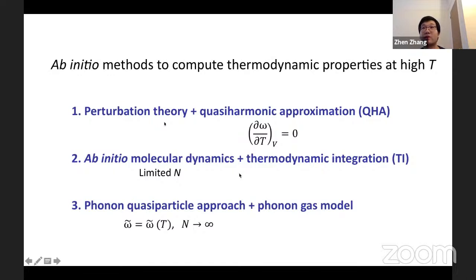Ab initio molecular dynamics plus the thermodynamic integration is a widely used method for free energy calculations. However, to approach the thermodynamic limit, conducting TI using ab initio MD with a sufficiently large supercell is beyond the current computational capacity.